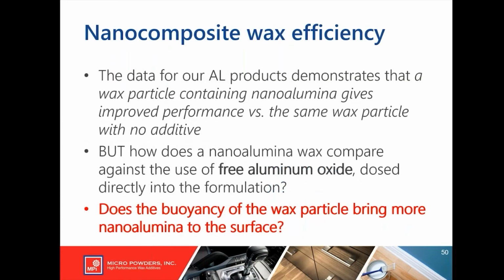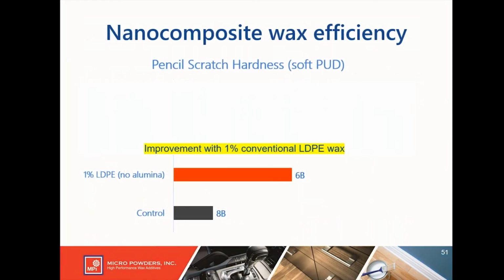So I am going to show you the data that I talked about before about if you're putting free aluminum oxide inside your formula, and that's been done for many years in things like high-end floor finishes. But we're going to show you that by putting aluminum oxide inside the wax particle, you get more of those particles to the surface. You get better performance. So here, control pencil scratch hardness, soft PUD, control is 8B.